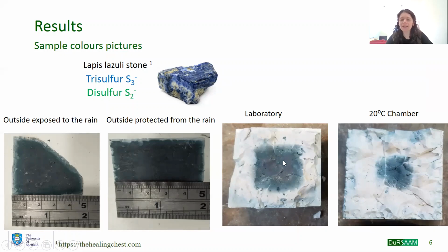red, green-ish, which is one form of sulfur. And after you have this green-blue, which is another oxidation state of the sulfur. And you can see also a white part and also a white, green, gray part for the samples inside. And for the samples outside, we can observe only this white part, which is really low.